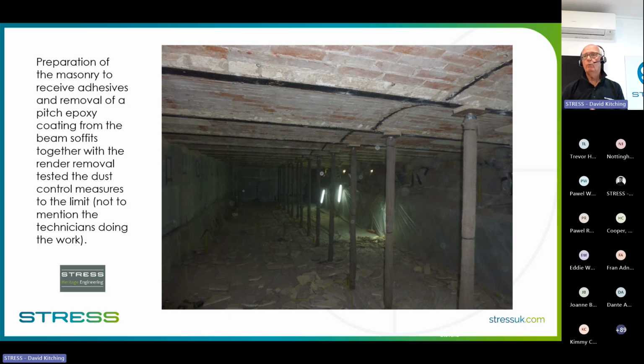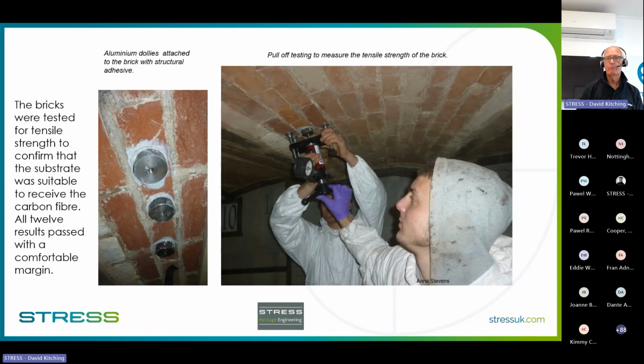That's everything, because as you know, if you put a piece of tape on something to hold things together and it's slightly damp or there's dust on it, tape just falls off. Exactly the same with carbon fiber. If you don't get the bond to the substrate, you might as well have used duct tape. So that's the key to everything. So it's got to be cleaned. You don't sort of jet wash this sort of stuff, but it literally has to be vacuumed, wiped down, and then ready.